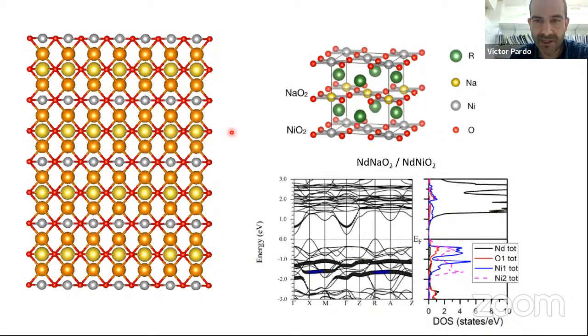You could also study this. This is a toy system, of course. What we did was a 1-1 multilayer of neodymium sodium O2 and neodymium nickel O2. What this does is produce a nickel O2 plane together with a sodium O2 plane, and this kills the off-plane nickel-nickel hopping. But the neodymium would still exist. So if the bands that cross the Fermi level in the bulk compound are produced by neodymium hopping, this would still exist here. But we see that is not the case. When you look at the band structure, the system has a gap.